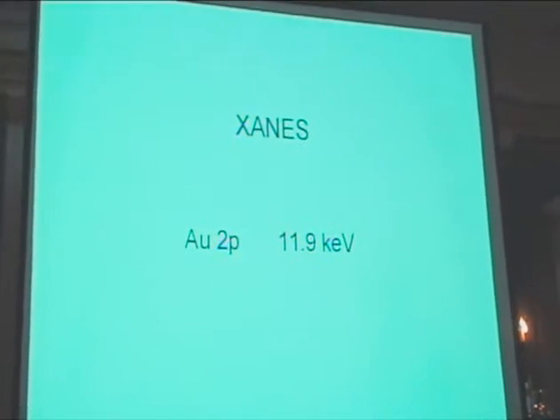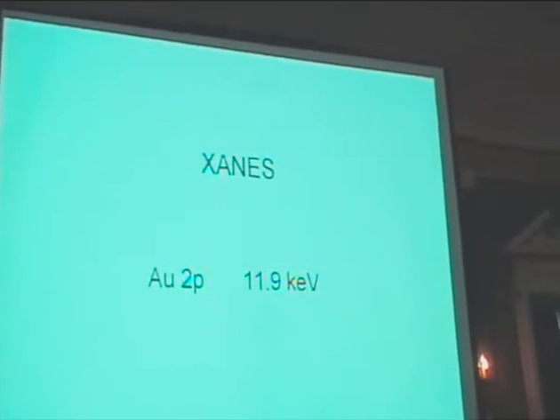Let me give you one more example of XANES, and that is gold. Gold, of course, has become a bandwagon in catalysis. Since people are working on fuel cells, you have to remove the last traces of CO. And one way of doing it, and Haruta discovered that, is take gold. You can oxidize the CO on gold, because gold absorbs the oxygen well and can split it. But gold has very great difficulty splitting the hydrogen. So if you have a mixture of a lot of hydrogen and a little bit of CO, it's the CO which can be oxidized to CO2 and then can be removed. Whereas you don't waste the hydrogen going to water.